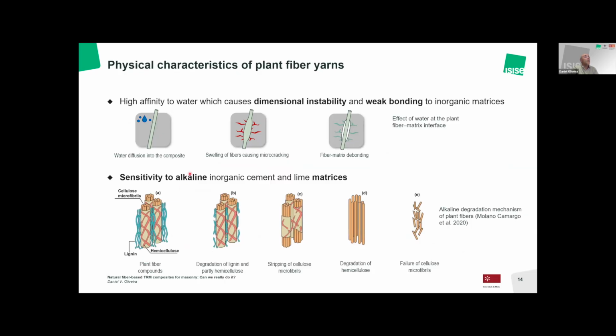Another problem is the affinity with water. So you are putting these fibers inside a mortar, and you may have this exchange of water, and this may be causing problems to your fibers. And this is also important in the long term. And finally, natural fibers are sensitive to the alkaline attack from the mortar. So you need somehow to protect them from this attack, which will definitely bring problems in the long term.